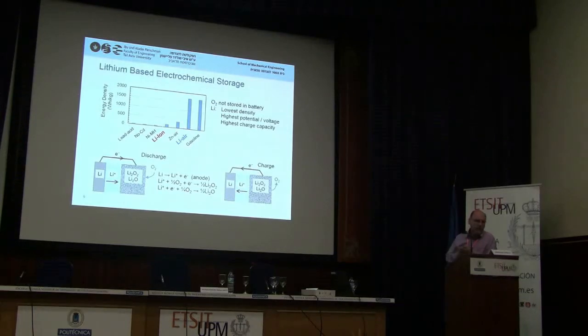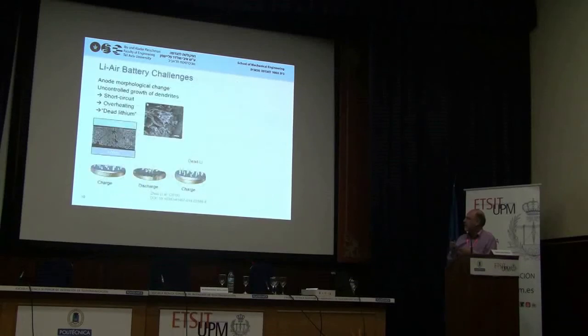So why is it not used today? And the answer is there are some fundamental problems that I will show in a moment. So basically what we have here is an electrode of pure lithium, a membrane that allows the transport of lithium ions back and forth. And here we get lithium oxide with oxygen that comes from the outside. And when we charge, we have to decompose these lithium oxides, and the lithium migrates back to this electrode.